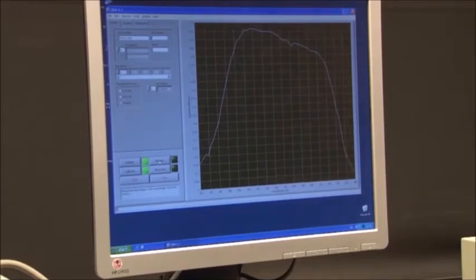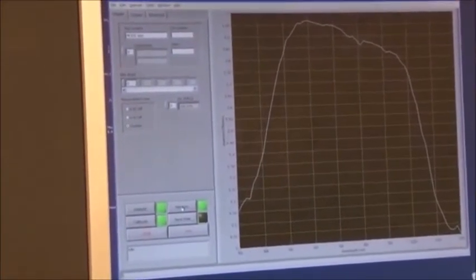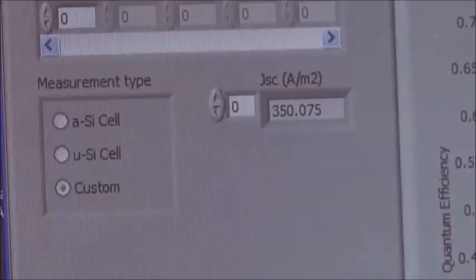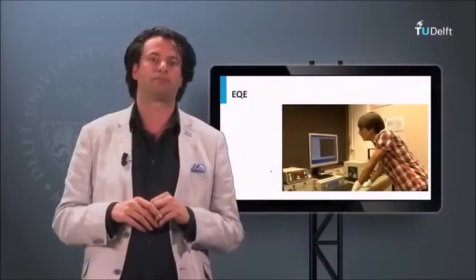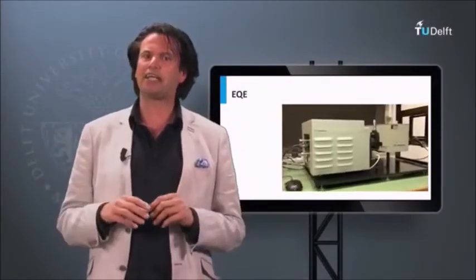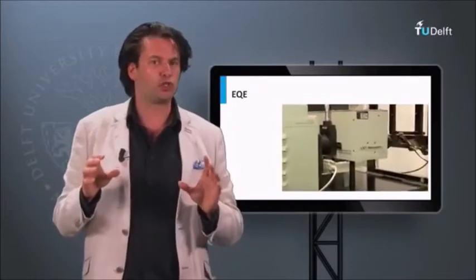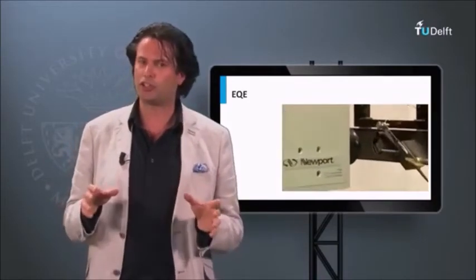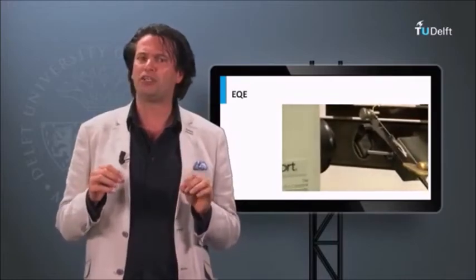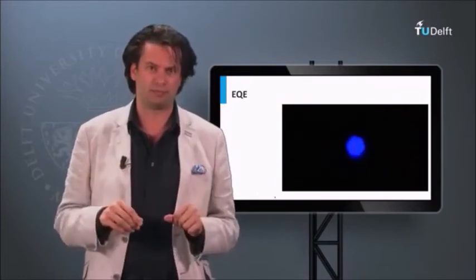As we will discuss in a minute, the measured EQE in combination with the spectral power density of the AM1.5 solar spectrum gives us the short circuit current density of the solar cell. In this case, the current density of the lab cell studied is 350 amps per square meter, or in a more practical unit on lab scale, 35 milliamps per square centimeter. Important to realize is that if you want to report short circuit current densities of solar cells, you cannot rely on a single JV measurement. They have to be measured using an EQE setup.